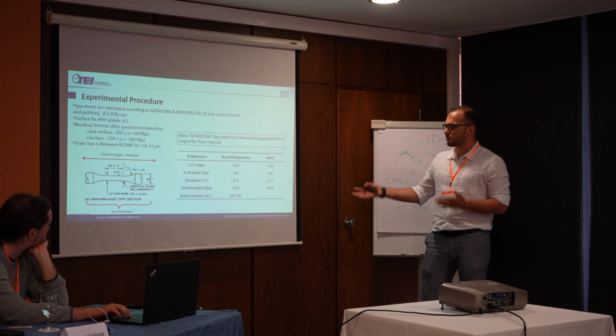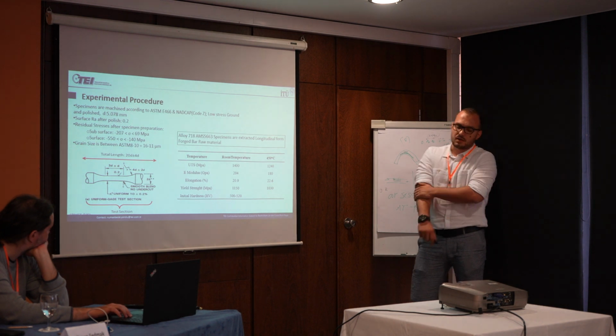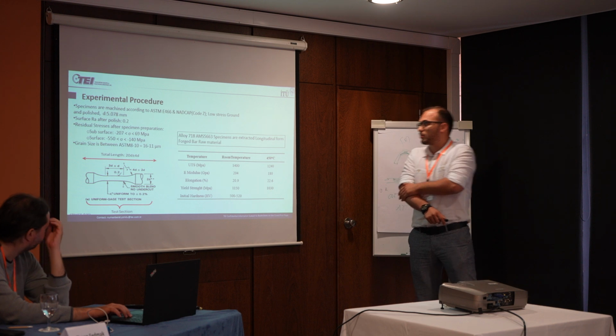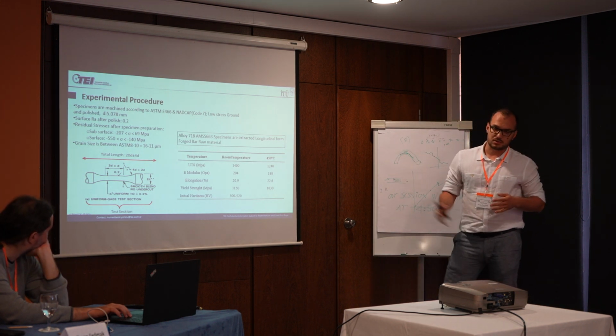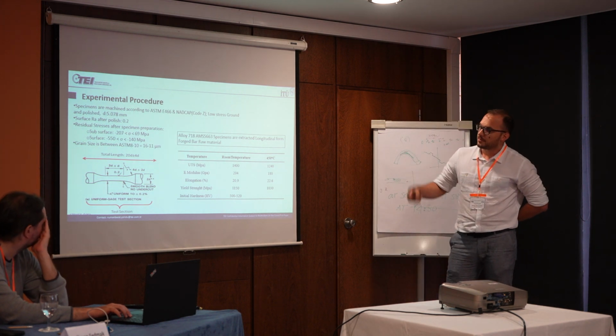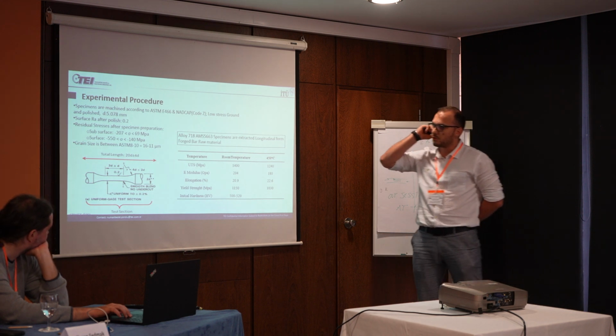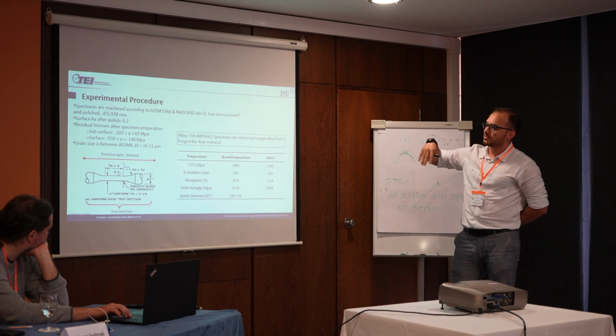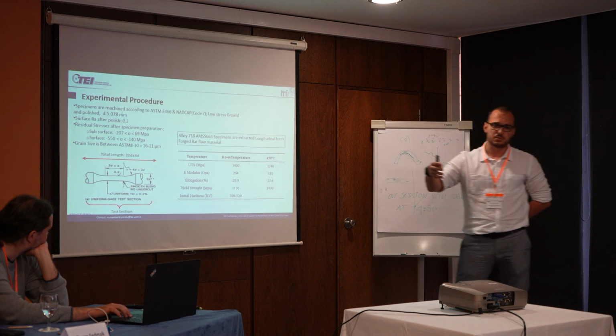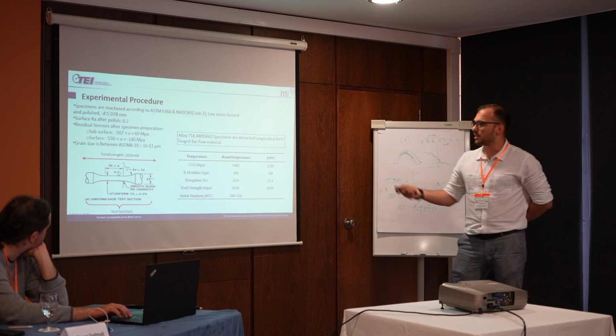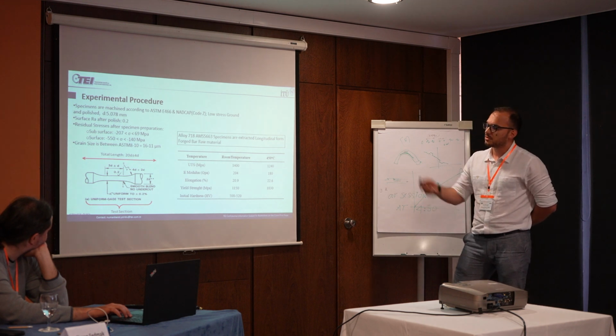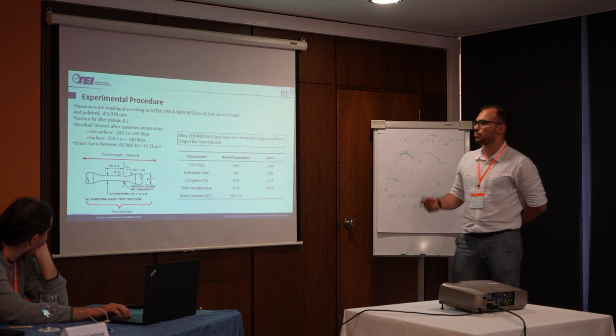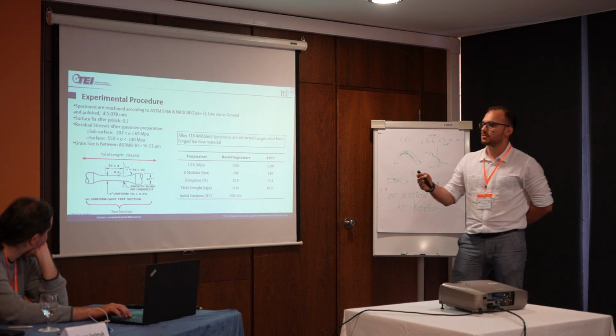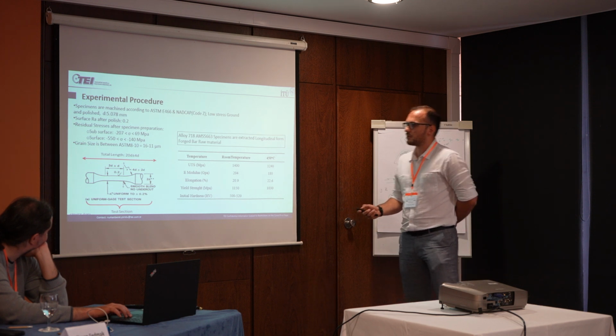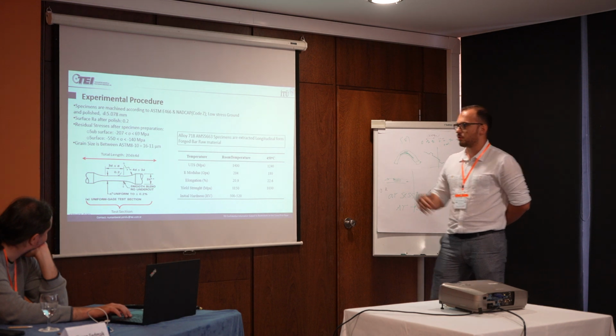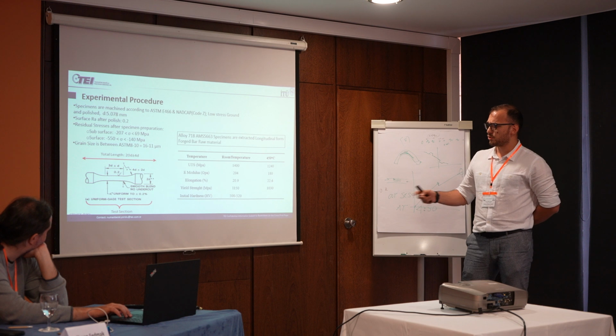Next slide. What we used in our tests was Alloy 718, AMS 5663, extracted from the longitudinal direction of forged bars, and we machined our specimens according to ASTM E466 and NADCAP code Z, which is a consortium defining the requirements of mechanical testing in the aviation industry. Our specimens have a surface roughness value of roughly 0.2 and have compressive stresses at the surface and subsurface, but these are relatively low compressive stresses, and we have these values for all our specimens.